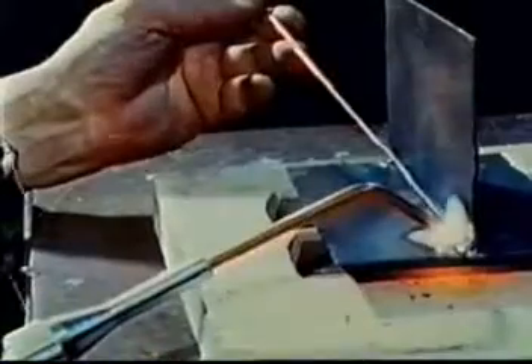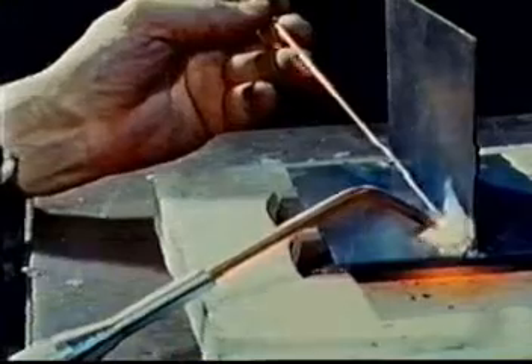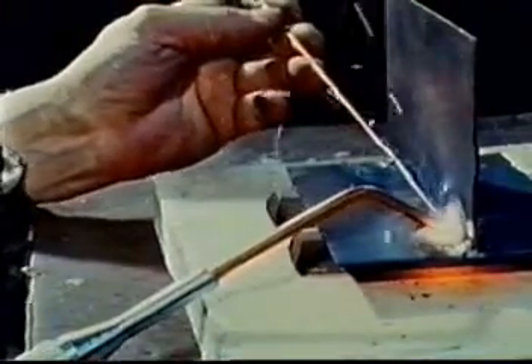The most common faults in fillet welding are holding the flame at the wrong angle and too near the vertical plate, which distributes the heat unequally so that you eventually burn a hole. Melting the filler rod before the parent metal so that metal drips onto the base plate where it gets blown into the root and sticks instead of fusing. Too much bead on the base plate with too little leg length on the vertical plate, resulting in undercutting.